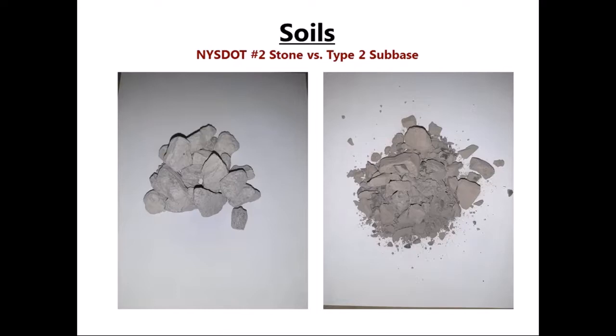But one of the things with this is in the field, because it is such a coarse material, it's not possible to do the typical field compaction testing on this material to verify it's compact. But because it is open graded, typically the specification is to compact it 4 to 6 times with a certain size compactor. The photo on the right, this is a type 2 subbase, and this is a material you typically see below a slab or below a pavement. And it's a well-graded processed material. And because of the fine content in it, it can be tested in the field for compaction in accordance with the typical project specifications.